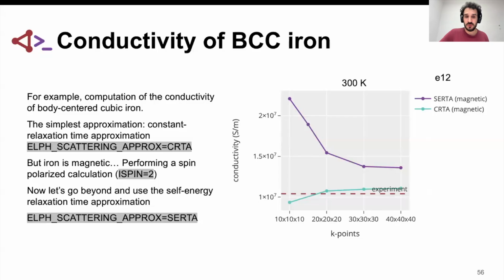If we go beyond this constant relaxation time approximation and use the self-energy relaxation time approximation, these are the values that we get. So before we were in this teal line, and now we get this purple line. So we are above experiment, way above experiment. So we have a better agreement when we were doing the constant relaxation approximation. What is happening?